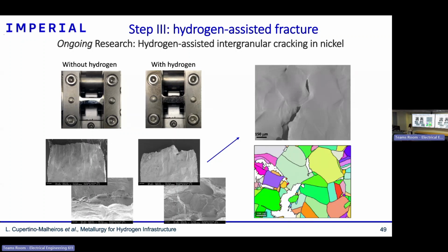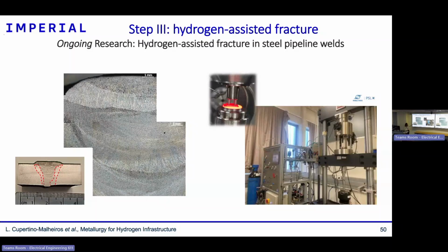Another ongoing research of a student of mine, we are now looking at the welds of pipelines for the current gas grid. So pipelines from different ages, some more modern from the 90s, some vintage from the 70s. And those welds in those pipelines are the weakest link for fracture. As there is an interest to repurpose this natural gas grid for hydrogen, and there is an interest for economical reasons that we can put high pressure hydrogen in the network, we are then investigating those welds to understand better the hydrogen diffusion and trapping behavior inside them, and also, in partnership with Paris, testing then on high pressures of hydrogen the different parts of the welds that have this beautiful microstructure that can be quite challenging sometimes.